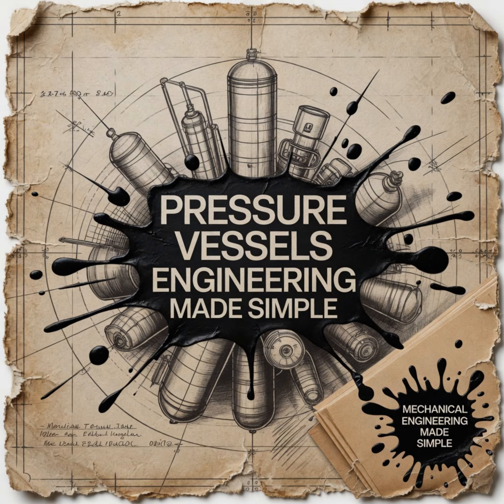An engineer can draw a perfectly circular, mathematically flawless cylinder on a screen, but you have to physically create that cylinder by feeding massive, flat steel plates through heavy rolling machines. Right, you have to bend it. And the laws of physics conspire against perfection here. When you roll a thick plate, say over an inch thick, the outer fibers yield in tension and the inner fibers yield in compression. Okay, that makes sense. But the core of the plate remains elastic. When the plate exits the rolls, that elastic core tries to return to its original flat shape. Oh. The cylinder springs back, it opens up. It is never perfectly round.